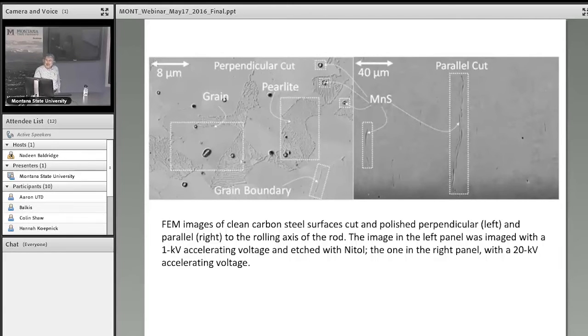But if you cut it parallel to the rolling direction, polish and take a look at it, you see that these manganese sulfide inclusions are really long, like a worm, extending hundreds of microns into the iron. In fact, there are about 3,000 or 4,000 of them per square millimeter in a given normal iron. If you get rid of these inclusions, you will have huge milestones covered in terms of protecting iron from pitting. We call them stringers. They run parallel to the rolling direction, but you only see the tips like that.